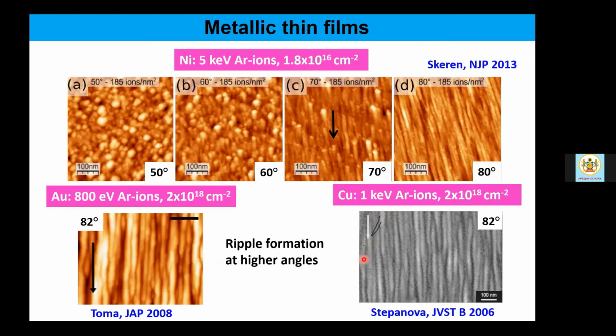But the important fact is, using energy in the tune of a few hundreds of electron volt to a couple of keV, and using different target material, using the same argon ions, people had reported nearly similar results of ripple formation at very high incident angle. But for silicon, if you recall, we saw ripple formation at a much lower angle.